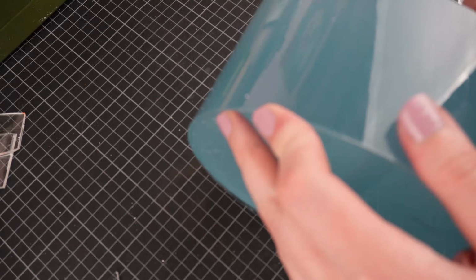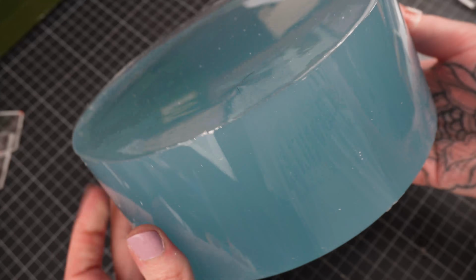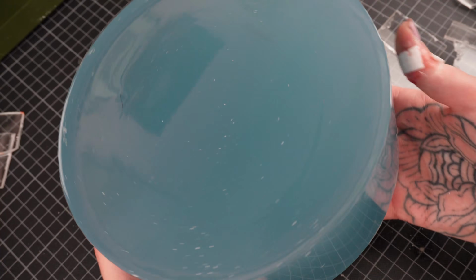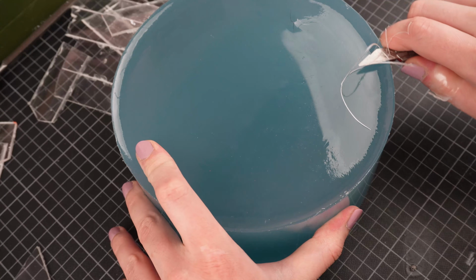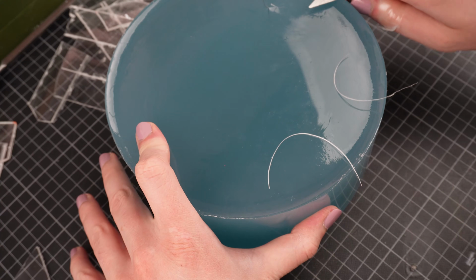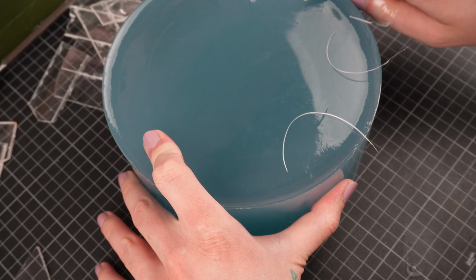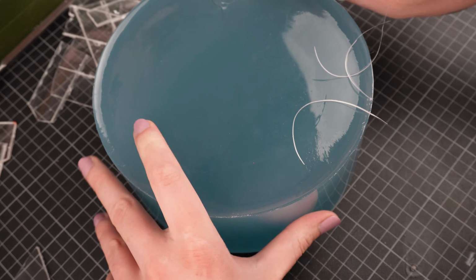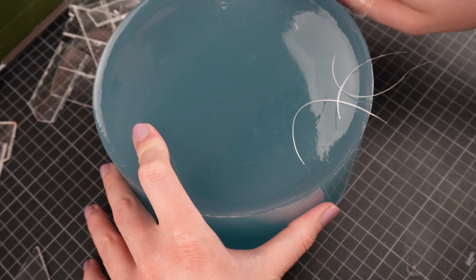Oh, and in case you wonder why there was so much silicone and hot glue on the mold for this fourth block, for some reason this mold wasn't leak proof, and after a couple of hours resin started to leak out of this one. So I used generous amounts of silicone and hot glue to close up the mold, and as you can see, luckily that worked as well. And you can't imagine how happy I was after this one finally worked out.